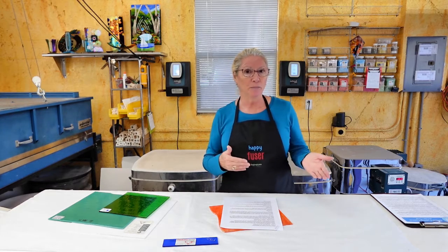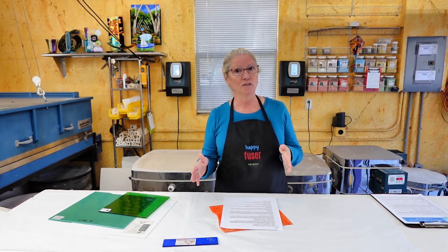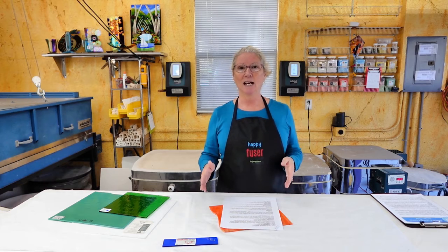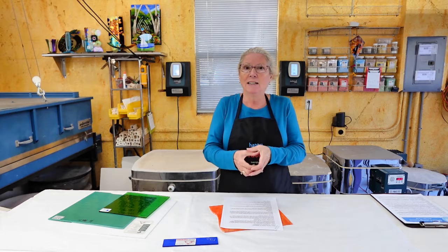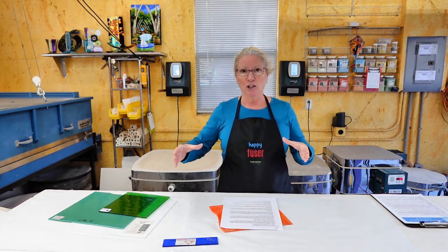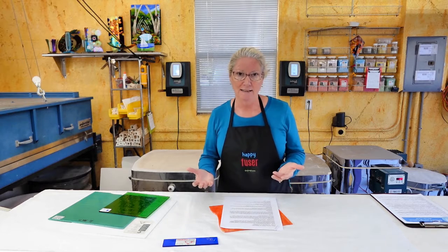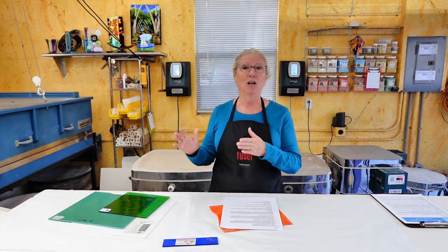Now, the annealing temperature is specific to the different manufacturers. They each have their own number that they like to use. Also, the amount of time that you use for that annealing, how long that will take, is determined by the size and thickness of your project. A tiny little project like this can anneal very quickly. A much larger project that is thicker, there's more mass, more glass, and that would take more time to anneal, so you would hold it there longer.